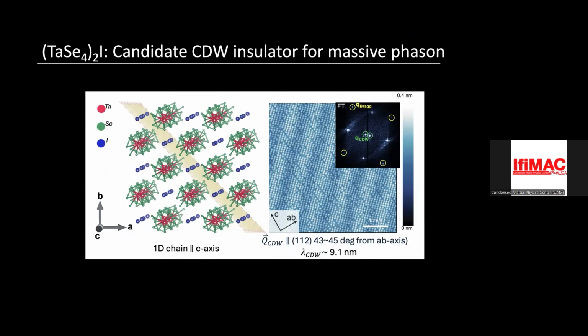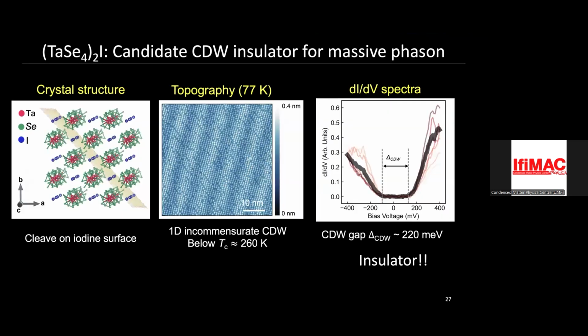This is what the STM image of the CDW looks like. You can see these stripes. This is the charge density wave. And in the Fourier transform, you can see it's these two dots. It's incommensurate. This is a pretty large wavelength CDW. And it's not even in the primary directions of the atoms. It's in some strange 43 to 45 degrees. It's huge. It's 9 nanometers, the period of the CDW. So you can see from STM spectra that it's got a pretty large gap. 2 delta is 220 meV, and it's a very robust insulator.